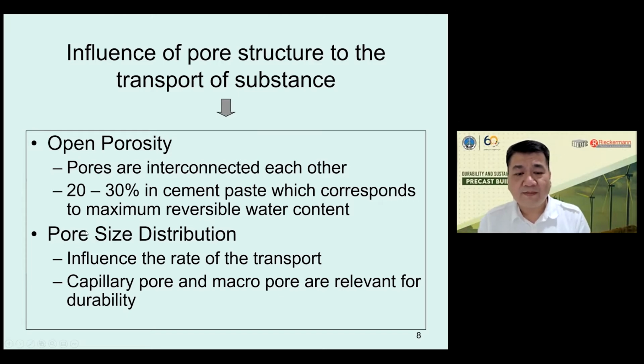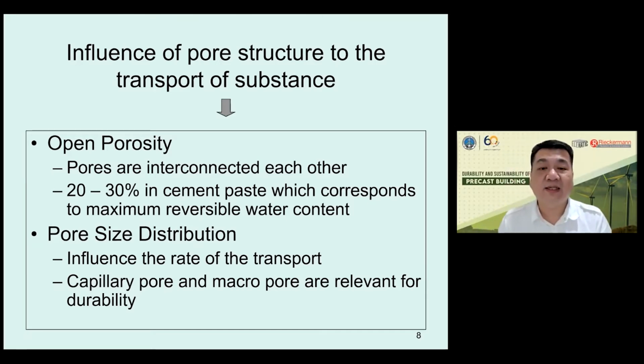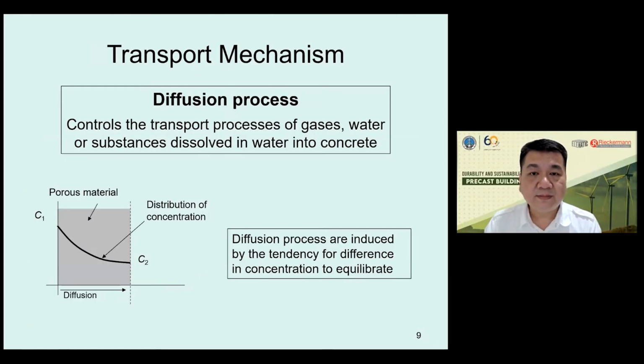And also one important thing to notice is the size distribution of the pores. Because when we have a very good concrete, the pores are so fine that the material from outside cannot enter. But normal strength concrete has a larger pore distribution, and then the material from outside can enter easily. This is just the basic for the transport mechanism.